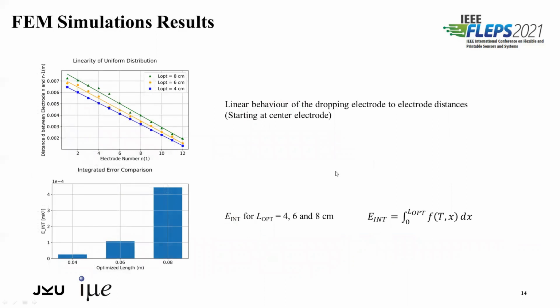So how can we describe the obtained distribution mathematically? If we start at the center electrode and plot the distances from one electrode to the next neighboring electrode over the electrode number, we get the linear behavior of dropping distances. This behavior is the same for different optimization lengths. The difference lies in the integrated error if we keep the number of the distributable electrode lines constant. It's obvious that the uniformity of the temperature is harder to preserve for larger optimization areas or optimization length if the electrode number is held constant. This can be seen in the bottom figure, where the integrated error is plotted against the optimization length.